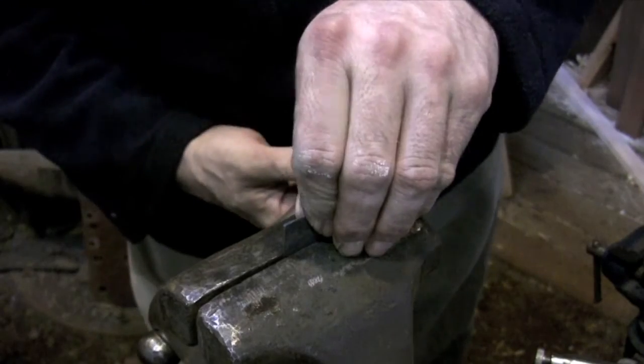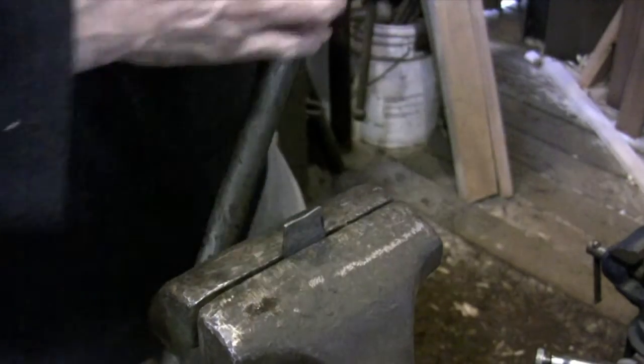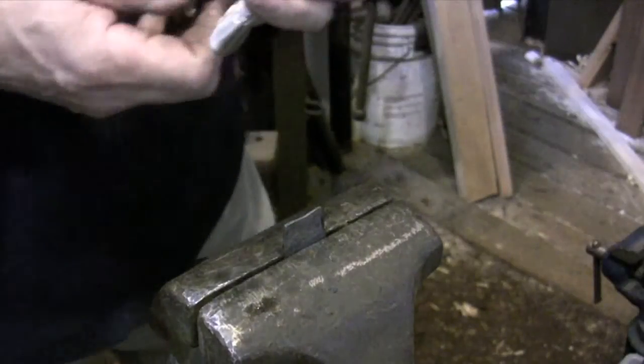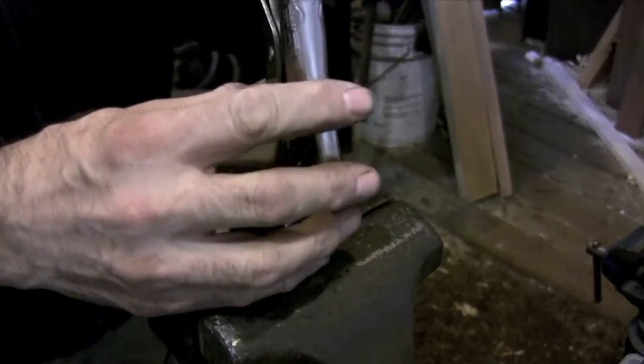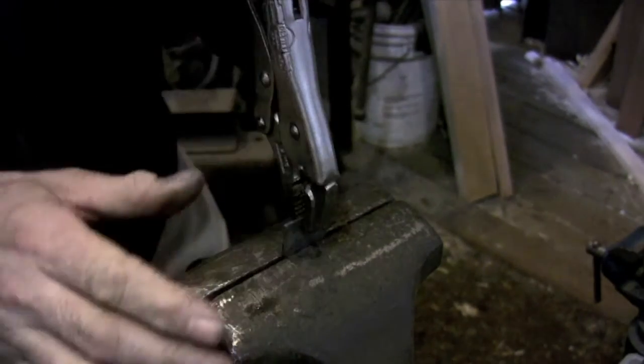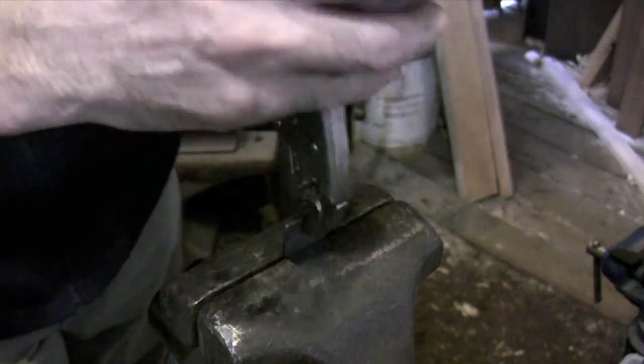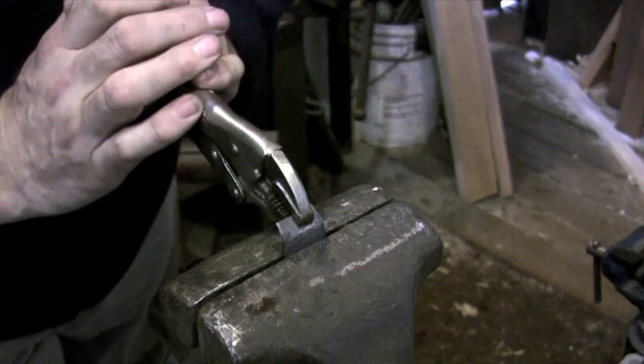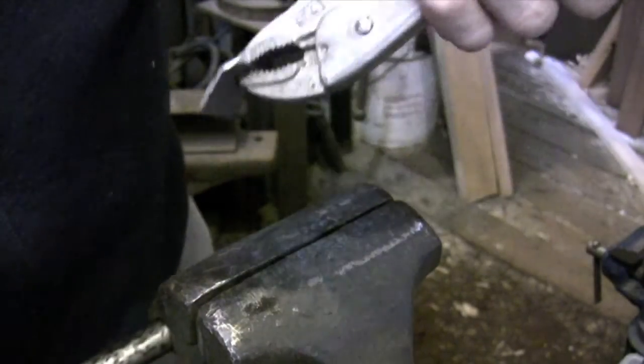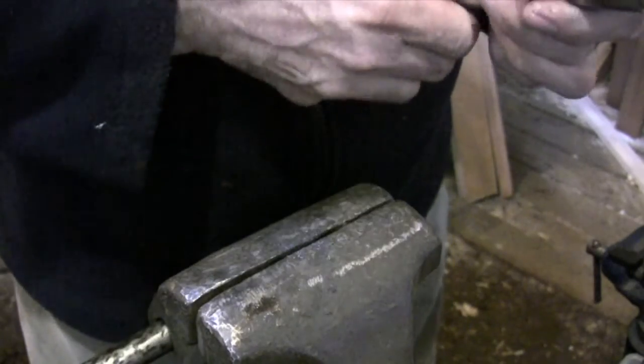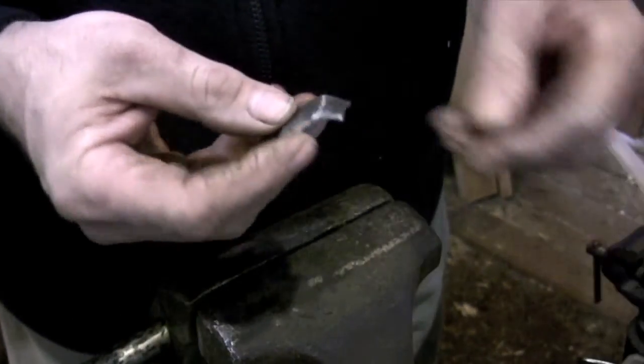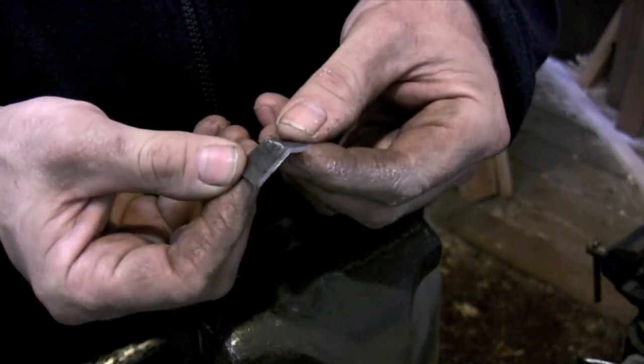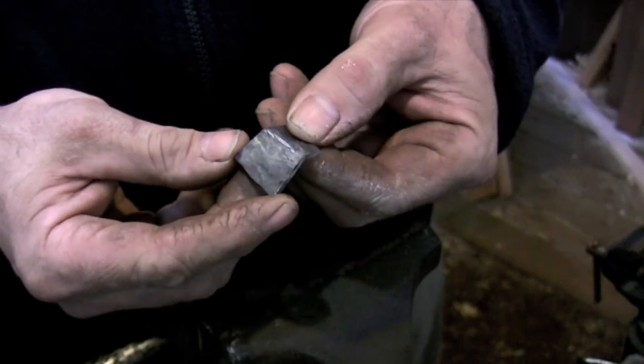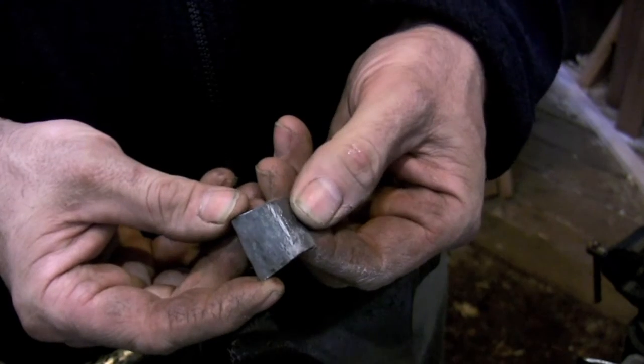The third sample piece is showing the completed weld. I'm able to flex the test piece back and forth until the steel starts to break at a stress point where the locking pliers were placed. The weld itself did not break. So you can see the difference that the additional forge weld made. Even though forge welding is considered a mechanical bonding of two surfaces, this sample is acting like one seamless piece of steel. The two faces have been locked together to such a degree that they are now as strong as the surrounding steel.